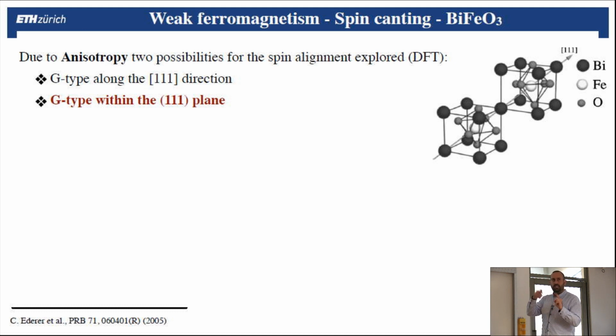And I told you that it was G-type, meaning opposite spin in plane and out of plane. And I showed you that this was the structure. So from this, due to the anisotropy, you can imagine two possibilities for the direction of your spins. First would be the 1-1-1 direction, so the diagonal here. So you could have a spin down here and a spin up here, parallel to this 1-1-1 direction. Another possibility would be to have the spins in the plane perpendicular to this 1-1-1 direction, with, for example, in that direction one spin and in the opposite direction the other spin. And using density functional theory calculations, which are numeric solutions of the Schrödinger equation for materials, one can compute these two configurations, compare the energy and find that this is the lowest energy one, meaning that the spins should be perpendicular in the plane here.